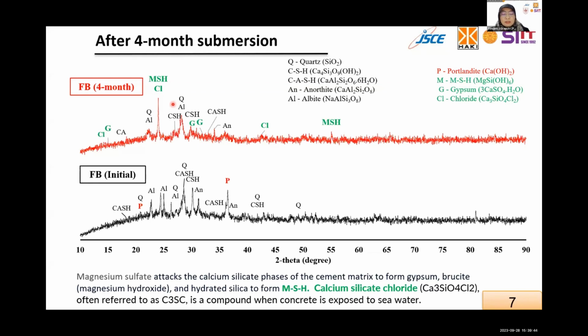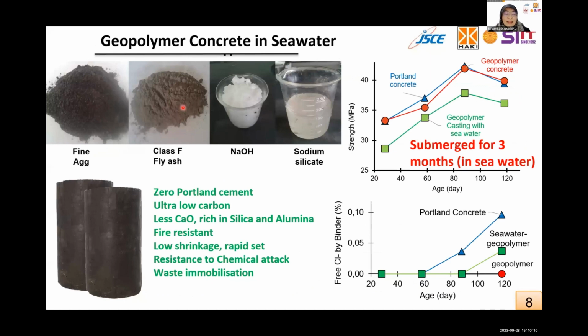And finally, it is proof that the sulfate and chloride ion decompose the calcium silicate hydrate product. And we understand that calcium-based material is still very weak against the aggressive ion. Then it is a very good idea to use very low calcium materials to cover and protect the existing concrete. Then let us see something very good about geopolymer concrete.